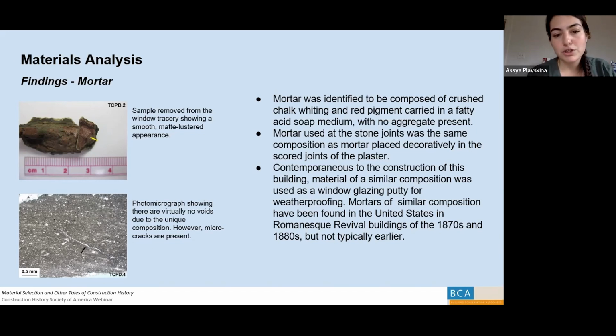Our goal was to install replacement mortar to match this everywhere there had been previous repointing or missing or failing mortar. So we were able to work with Limeworks to create a great replacement mortar that had some of the properties that we needed that were more appropriate for window tracery joints, for example, but had this very similar smooth matte lustered appearance that we had in that original pointing mortar.